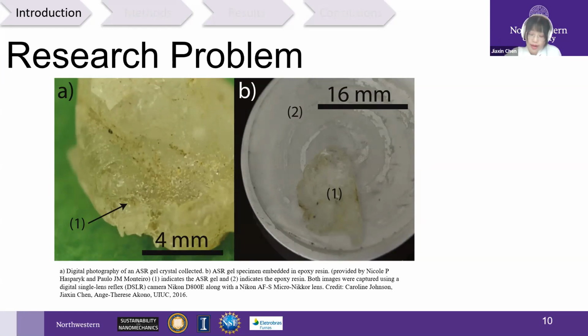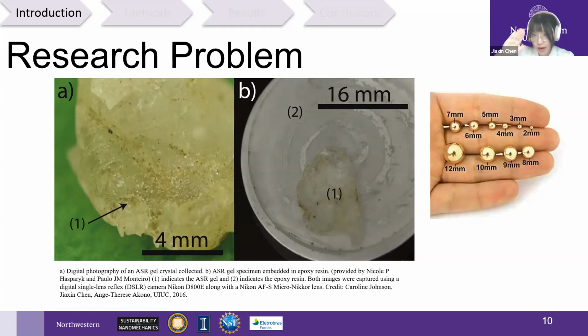How can we characterize the fracture behavior of this small gel? From the image, it has a scale bar of 4 millimeters, for the US system, which is around 0.16 inches. To illustrate how small it is, I got one image online to show 4 millimeters in our hands. You can think of the size of an ASR gel crystal in your hand like that. It is so tiny that we cannot use the classical method to get its fracture toughness.